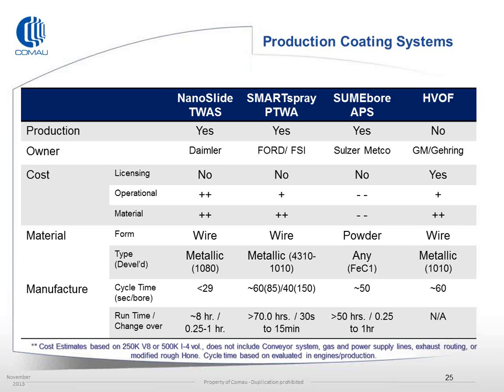the nanoslide uses a 1080 or a high carbon steel. The smart spray, with using a compressed air, can use as low as a 1010 and any high carbon or modified alloys. Cycle time for a nanoslide is typically 30-ish seconds. At 85 amps, we're around 60 for a 84 millimeter bore, 4-cylinder. At 150 amps, we're just under 40 seconds.